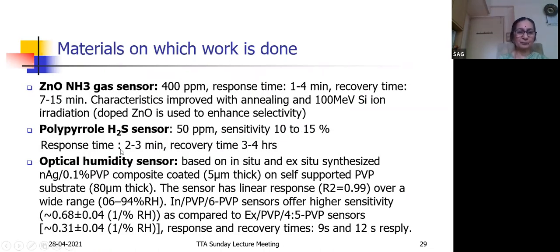There are a few which I'm describing over here, because I cannot describe all. This is just a sample. ZnO NH3 gas sensor. The ZnO sensor for NH3 gas was developed for 400 ppm. Response time was 1 to 4 minutes. Recovery time was 7 to 15 minutes.